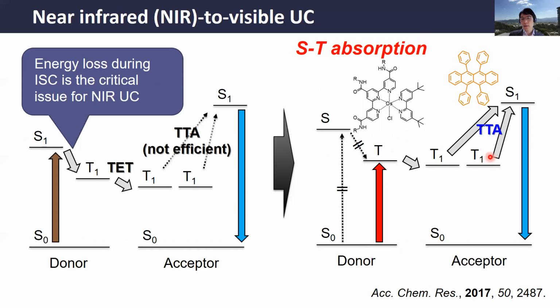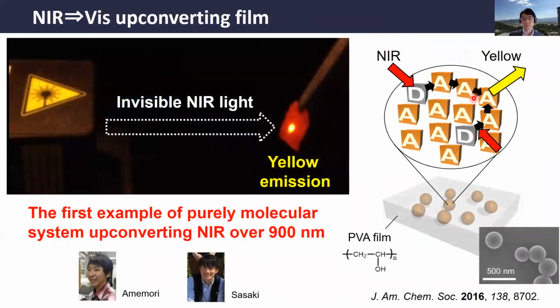And we combine this osmium complex with a rubrene acceptor. So we prepared rubrene amorphous nanoparticles and doped the osmium complex into these rubrene nanoparticles. And then we dispersed this in a PVA film that has good oxygen blocking ability. By shining invisible near-infrared light onto this film, we observe nice yellow upconverted emission in air.